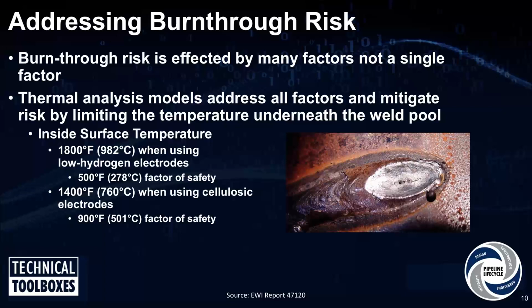Now, these limits aren't limits that some engineer just picked out of the air. When these thermal analysis models were being developed, and one of the earlier ones was in the late 70s, early 80s, what the engineers did at the time to validate their model was they instrumented pipe spools with thermocouples on the ID of the pipe. And then they drop those spools into a test loop, and they run, whether it's natural gas or propane, through the loop. And then they had the welder weld on the outside of the pipe directly over the thermocouples that were located on the ID of the pipe.